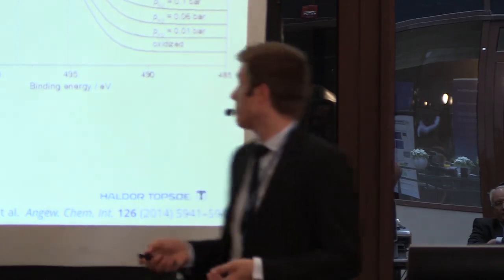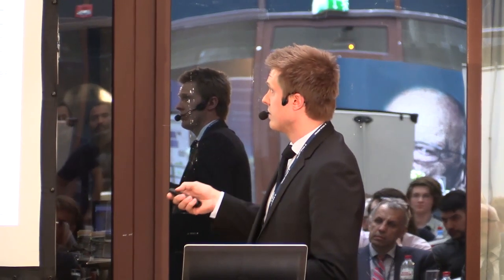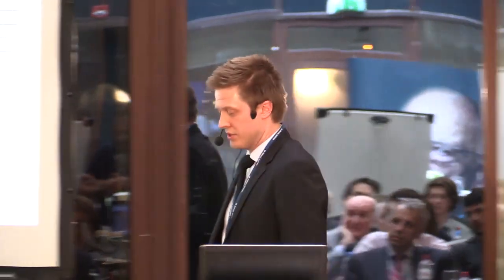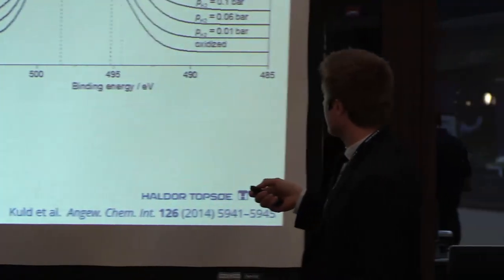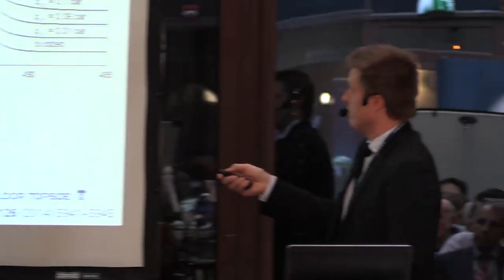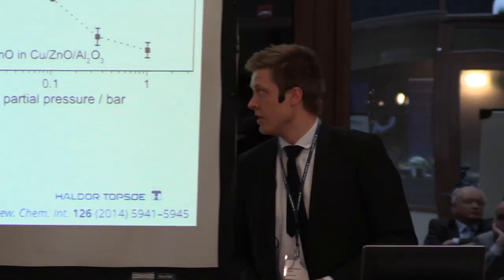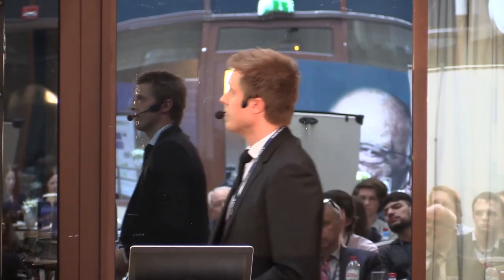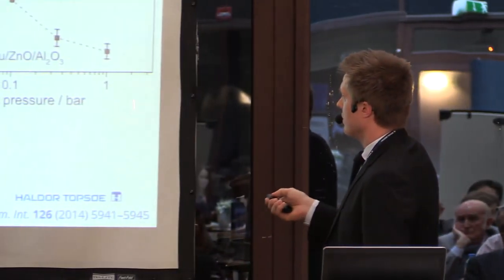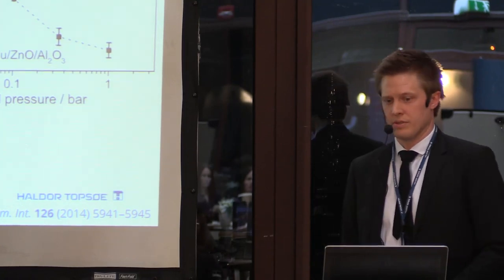So what we did was that we took the catalyst, we did some different pretreatments in different partial pressures of hydrogen, and then we can do this sort of analysis afterwards. So initially we have the oxidized catalyst, and then we gradually increase the partial pressure during the pretreatment and before the characterization. And what you can see here, very clearly, is that this shoulder feature is rising up. This is seen in another way here, where we have the relative fraction of reduced zinc in the surface as a function of the hydrogen partial pressure during the pretreatment.